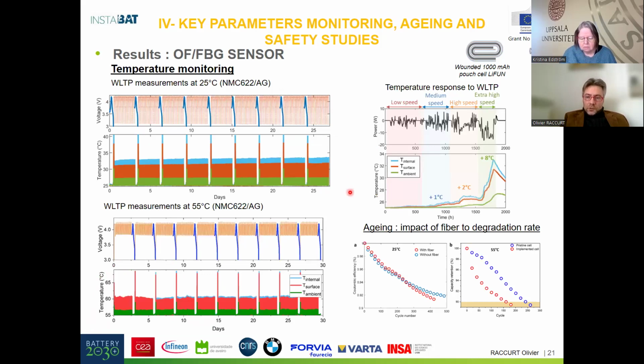Another result that I want to show you is about the aging. We use an internal FBG sensor to monitor the temperature of the cell inside and outside the cell during cycling. In this test, we use a Li-ion cell with a cycling test with WLTP. You can see here the different WLTP cycling, a long-term cycling, and then there is a checkup to measure the capacity of the cell at C/10 rate.